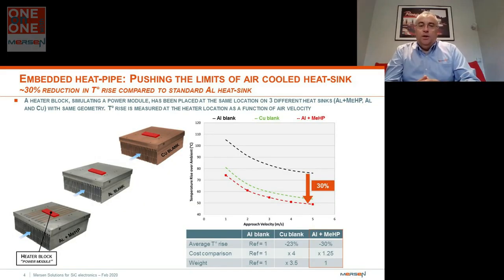So for the air-based, it's very difficult to efficiently cool down SiC using a simple, basic extruded heatsink. The reason is simple. The calories cannot spread over the base plate enough to be extracted from the fins. So we have to help the energy run through the base plate. And to do so, at Mersen, we have developed a nice technology dealing with embedded heat pipes. I don't want to enter the detail today, but a heat pipe helps really taking and capturing the energy, the calories here and transporting there.